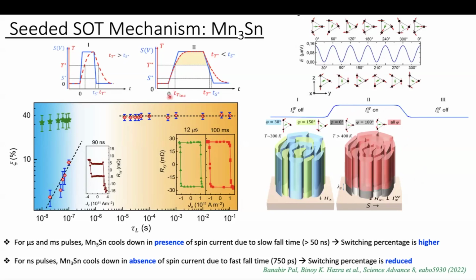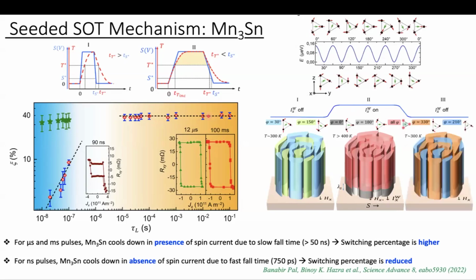Now in the case of a millisecond pulse, what happens? In the case of a millisecond pulse, the typical fall time is greater than 50 nanosecond. So the system gets enough time and relaxes in the presence of the spin current, and that's why it relaxes to the 210 or 330 domain structure. And then we observe the maximum switching percentage, that is 40%.